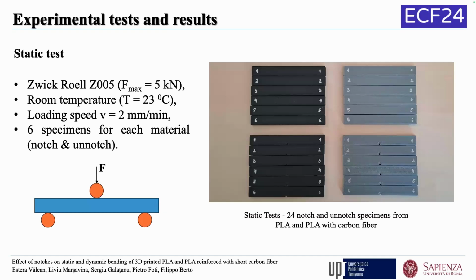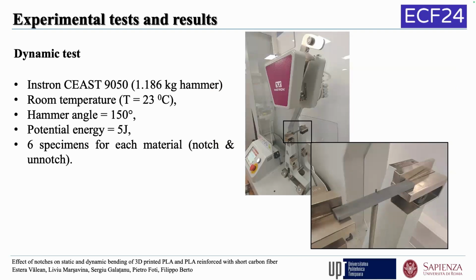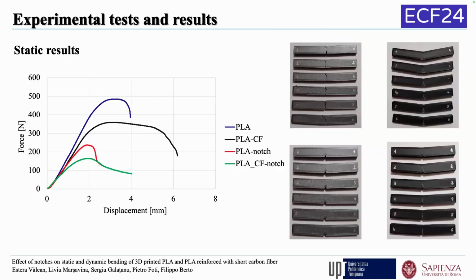The static tests, we did in our lab using a Zwick Roell universal testing machine at room temperature with a loading speed of 2 millimeters per minute, and we use 6 specimens, notched and unnotched, for each type of material. For the dynamic test, we use also an instrumented impact hammer, which is also in our lab. We did the test at room temperature. The potential energy of the hammer is 5 joules, and the initial angle for calculating the potential energy was 150 degrees. Also, 6 specimens for each material, notched and unnotched, we use.